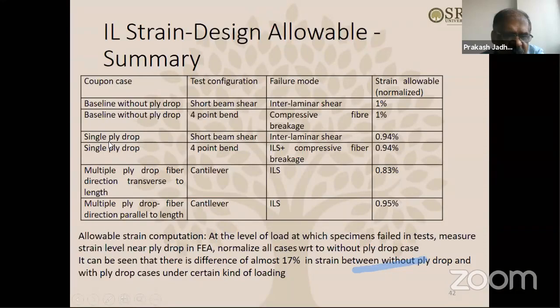Then how do you compare all these cases? So single ply drop and multiple ply drop under different conditions. Single ply drop under short beam shear and under 4-point bend. If you compare, then compared to this 1%, the strain level is 0.94, 0.94. What does it mean? It means the specimen with a single ply drop inside is going to fail at 0.94% strain as compared to the baseline specimen, which will fail at 1%. So presence of ply drop is making a difference. If a ply drop is present, it is going to fail early. And how much early? It is going to fail almost 0.06% strain early.